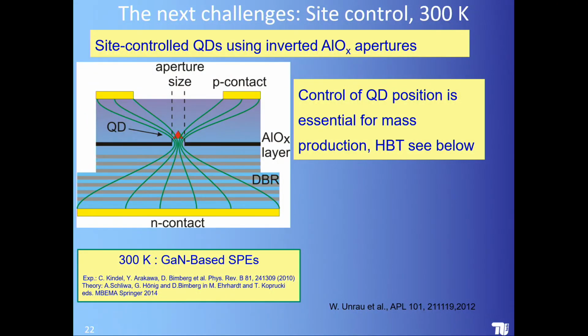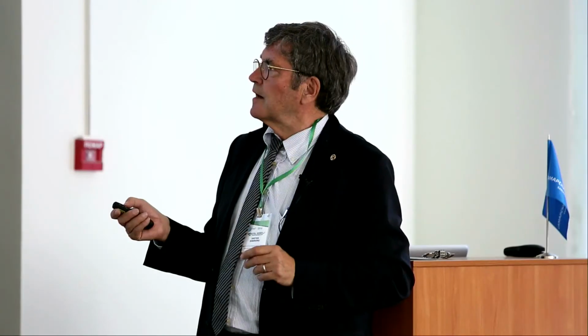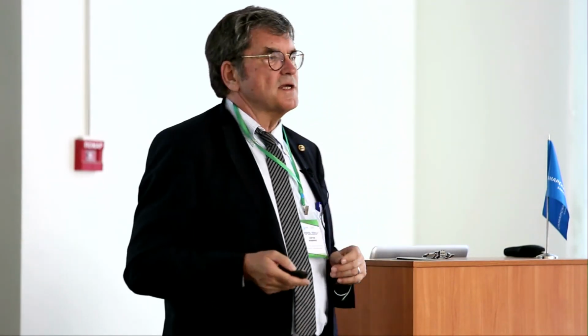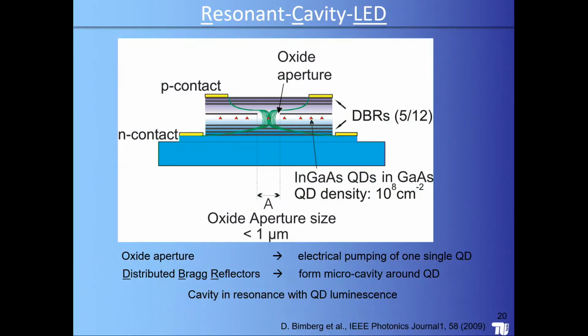Now, the problem is, of course, sometimes a quantum dot is below the oxide aperture, sometimes not. In about 98% of cases not. So the student who did that work had to search around 5,000 of such devices we had on one wafer until he found 10 where the quantum dot was really below. So this was an idea which could be improved.